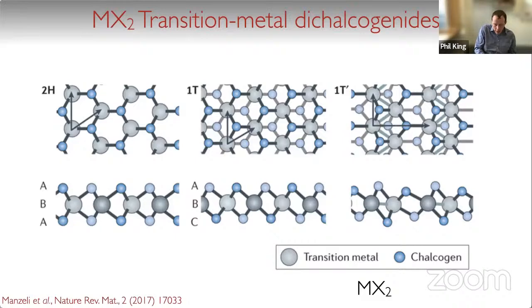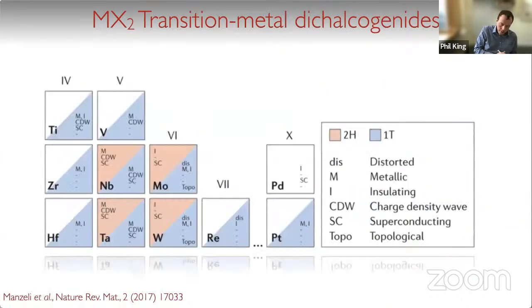And there's actually a few different structural polymorphs of these transition metal dichalcogenides. For example, in the 2H structure here, you have the chalcogens rotated in the same orientation in the plane above and below the transition metal. And much of what I talk about will actually be general across this class. But the key feature is we take these layers of transition metal chalcogenide octahedra, and then we stack these together with van der Waals interactions between the layers.